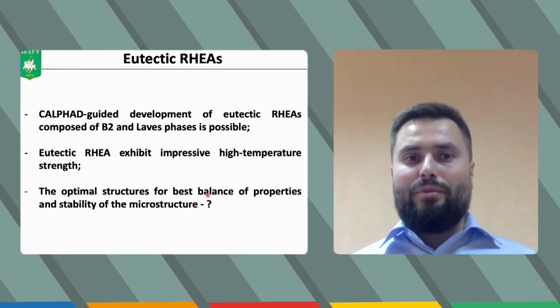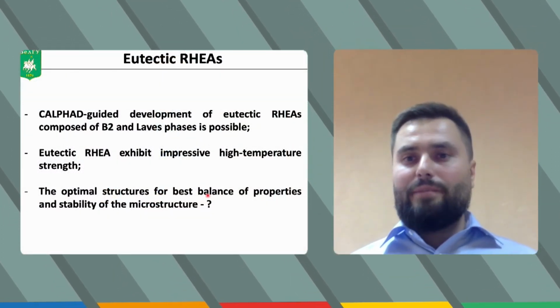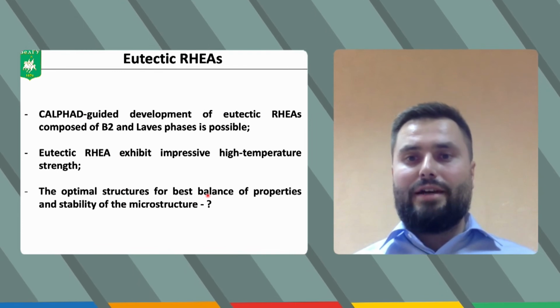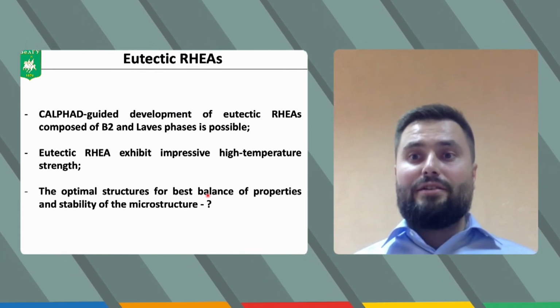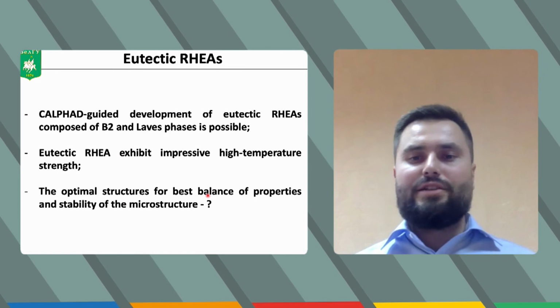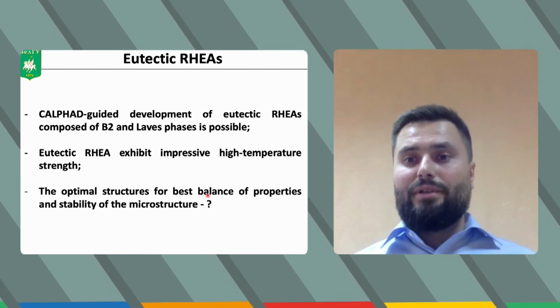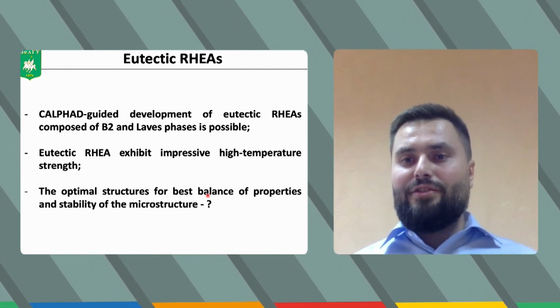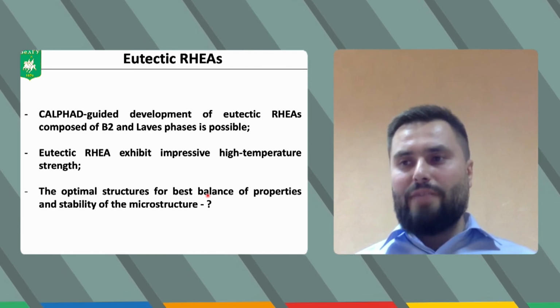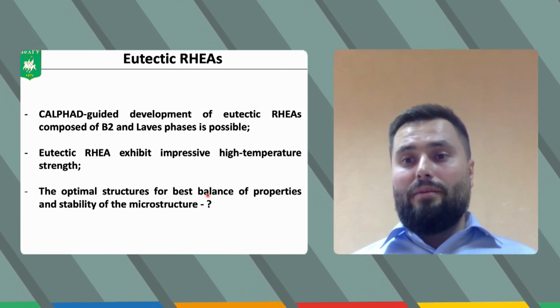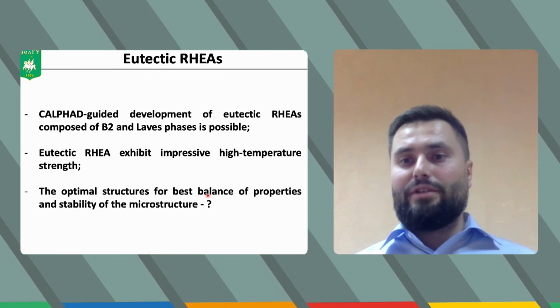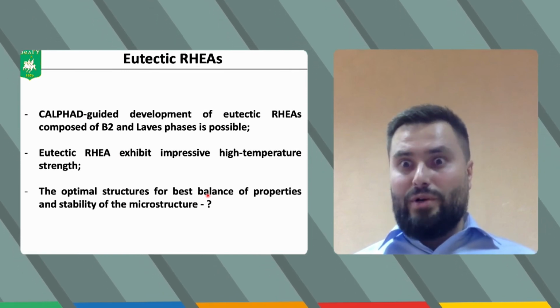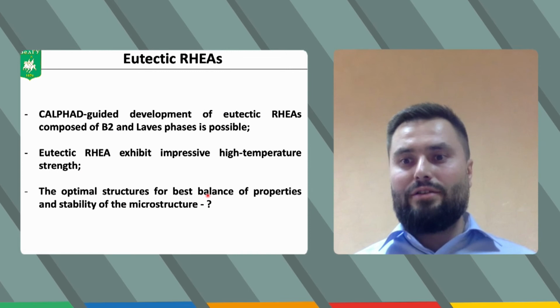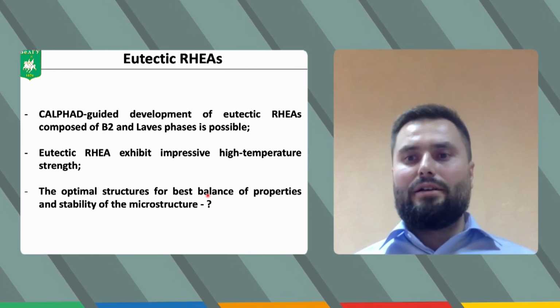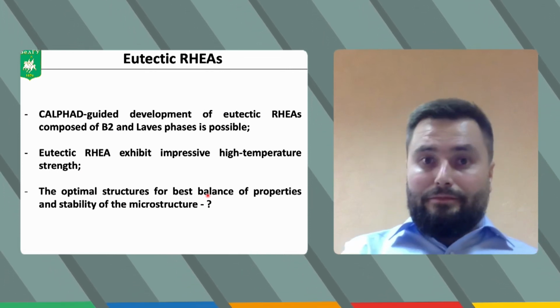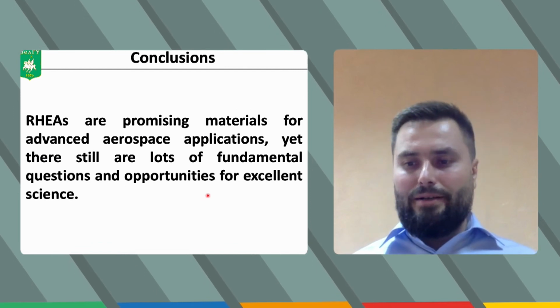We have performed the CALPHAD-guided development of eutectic refractory high entropy alloys here, and the obtained alloy has demonstrated quite good high temperature properties. And I strongly believe that we will be able to optimize the properties of these type of alloys. For example, improve the room temperature ductility in efficient way by performing simulations of the phase structure of these alloys. And that's the final.